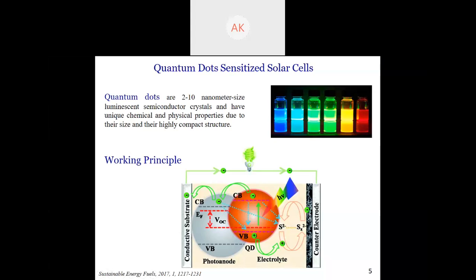Firstly, there can be an internal charge recombination, that is between the electron and the hole inside the quantum dot. There can be a back electron transfer from the electron in the conduction band of the photoanode to the valence band of the quantum dot. Similarly, there can also be recombination between the electrons in the conduction band of the photoanode and the oxidized species in the electrolyte. The oxidized species in the electrolyte have a tendency to take electrons from the conduction band of the photoanode or from the conduction band of the quantum dot. So these are pathways which need to be overcome if we are aiming at a high efficiency solar cell.